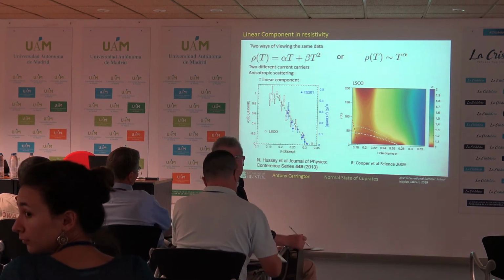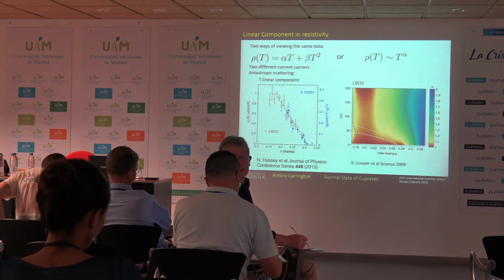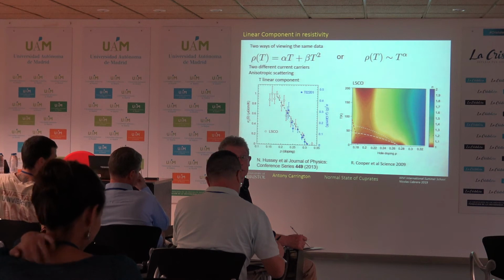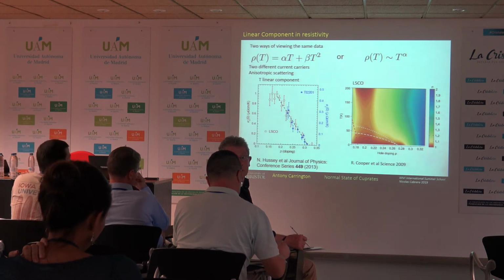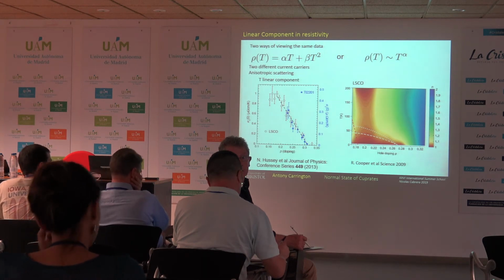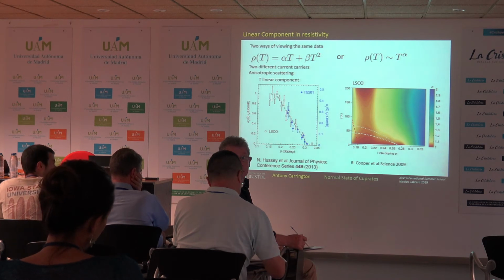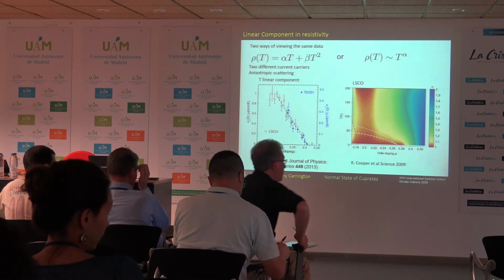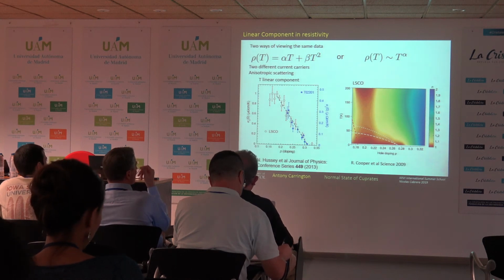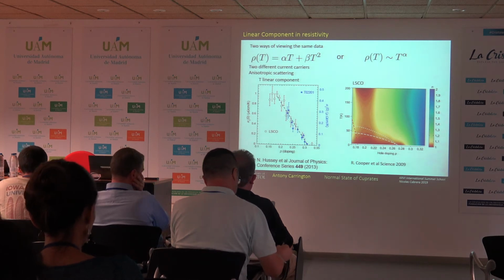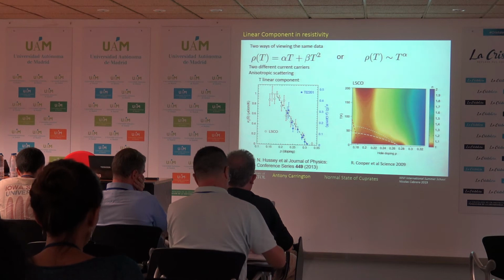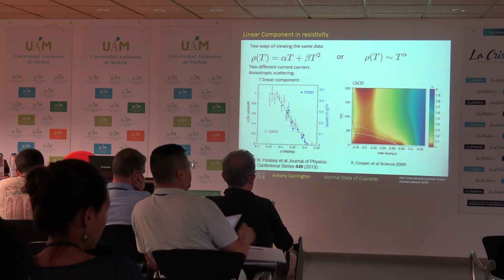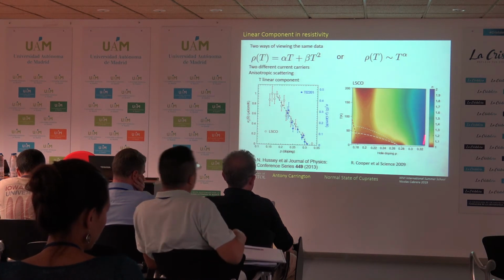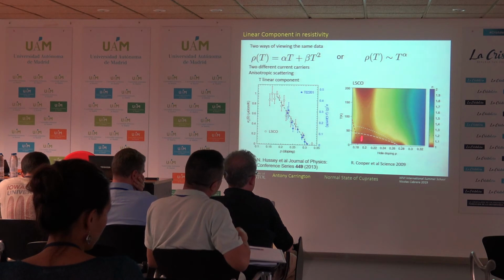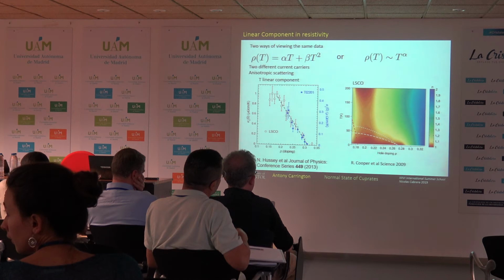Andre. Since Jörg asked a question. You started by showing us the data which shows linear in T resistivity up to 1000 Kelvin. Yes. Then you switch to data in the range between 100 and, say, 250 Kelvin, and did this splitting into linear in T and quadratic in T dependence. Yes. But my question is about experiment. If you look at temperatures above 250 Kelvin and follow what happens with that linear slope as you increase doping, what happens? I mean, this separation into linear and quadratic behavior shows that at higher temperatures you ought to have quadratic behavior, while originally you had linear behavior up to 1000 Kelvin. Yeah, okay, but that's only at one particular doping. So if you looked at this plot here, that's what this is saying, right? You've got this linear exponent that's going up to very high temperature. So beta is very small there. Yes.